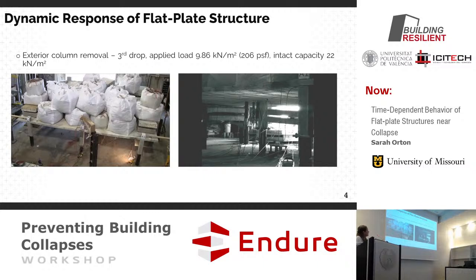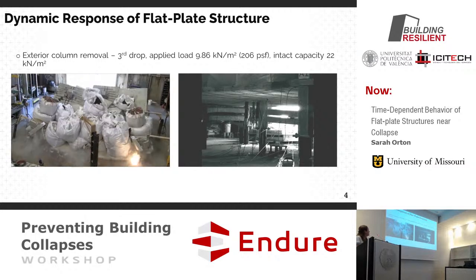And it will drop. The applied load was about 10 kilonewtons per meter squared. The intact capacity, if you had the column, would be about 22. So you're at about half of what the building would be able to withstand if it was fully intact. And you can see it didn't do so well. We did 2 previous drops before this at lesser load levels, and it didn't collapse, and so that's why we did the third.